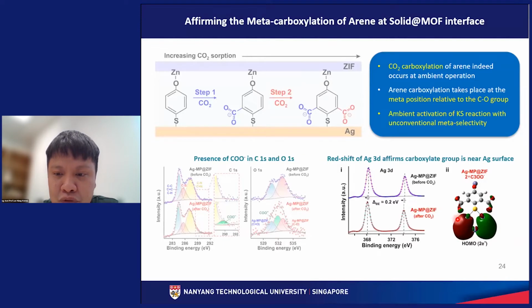that the HOMO comprises molecular orbital contributions from both the silver as well as the carboxylate group, right? So this tells us that electrons in the HOMO can be delocalized from our carboxylate to the silver. So this will ultimately lead to an increase in the electron density in our silver, and thereby lead to a red shift of our silver 3d peak towards a smaller binding energy. So through XPS, DFT, and SERS data, we can confirm that meta-carboxylation of arene indeed occurs at our solid-MOF interface.